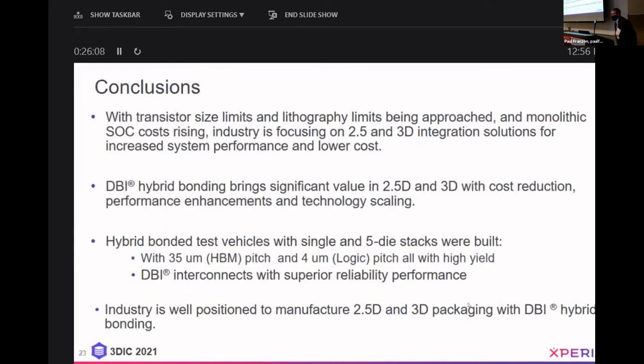So, in conclusion, with transistor size limits and lithography limits being approached and monolithic SoC costs rising, the industry is focusing on 2.5D and 3D integration solutions for increased system performance and lower cost. DBI hybrid bonding brings significant value to 2.5D and 3D with cost reduction, performance enhancements, and technology scaling. Hybrid bonded test vehicles with single and 5-die stacks have been built with 35 micron HBM-like pitch and 4 micron logic-like pitch, all with high electrical yield. The DBI interconnects have shown superior reliability performance. And basically, the industry should be well positioned to manufacture 2.5D and 3D packaging with this type of DBI hybrid bonding technology.